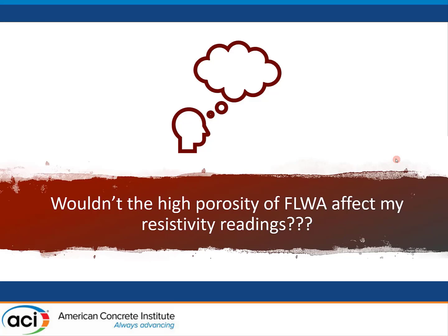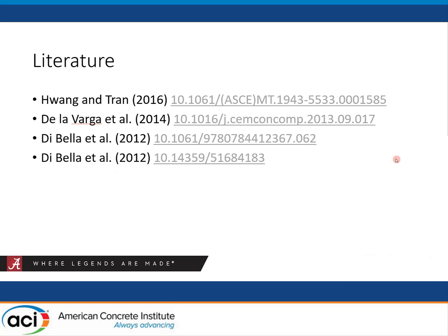And so I went to the literature and found that, okay, some people have measured resistivity of internally cured mixtures. The first reference there, Hwang and Tran, only looked at lightweight aggregate mixtures, so they didn't really have a comparison to just normal concrete. De la Varga looked at surface resistivity readings, which is very appropriate for a bridge deck kind of evaluation. DiBella, in both of those publications, looked at internally cured field mixtures, but they had been saturated, so they had been sitting in a lime bath their entire life, if you will.